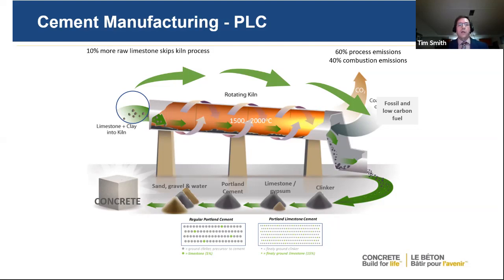What they do is they still have the grinding process. And when they're doing this, they actually grind the Blaine of the Portland limestone cement a little bit finer than the conventional GU cement. And that actually gives you some advantages from the strength side and the setting time. And then again, you just take the Portland limestone cement, you mix it with the fine and coarse aggregates, water, any admixtures to create your concrete. So it's the same process to create the clinker. It's the difference to create the cement itself.